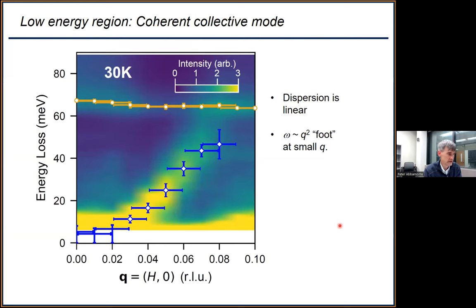It looks a little more compelling on a color plot. So this is just the same data. This is momentum on this axis, energy on this axis. So here's that conventional phonon. And now we've added points on the plot that came from some fits with error bars. And that's the dispersion of the mode. So it's not perfectly linear. It's got kind of a Q squared foot at small q. But then there it is. So the question is, what is this thing?